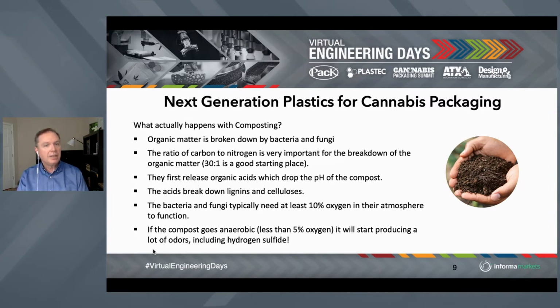And you see the last point there is that if the compost goes anaerobic, that is, if it's less than 5% oxygen, it'll start producing a lot of odors, and that includes hydrogen sulfide, otherwise known as rotten egg smell. So anyways, the industrial composting facilities try and maintain at least 10% oxygen in the atmosphere to function. One thing that I didn't list here is the necessity of moisture in the composting as well. That's a very important part of it as well.